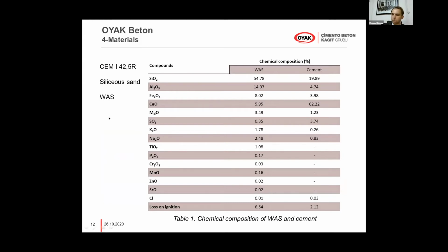And we can come to our experimental study. We use this washing aggregate sludge, VAS, obtained from the Oyak Ready-Mix Concrete Company, as I said, and we use one type of cement, which we obtained from Bolu Cement. This is also one of the Oyak companies. And silica sand. As you can see in the figure, there is the chemical composition of VAS and cement. The significant point of VAS is silicon dioxide, because its range is higher than 50%.